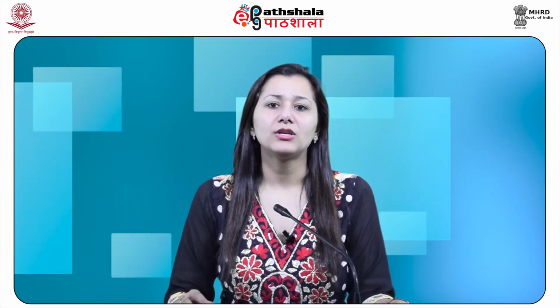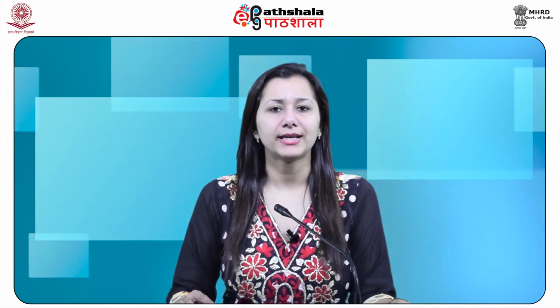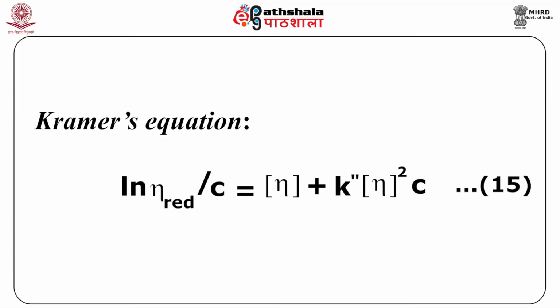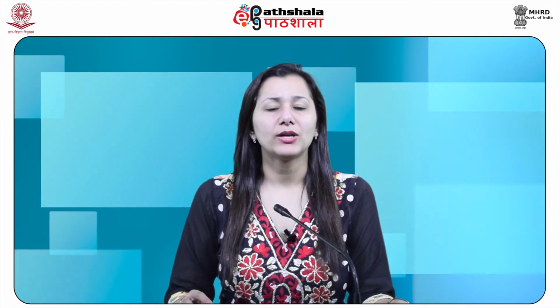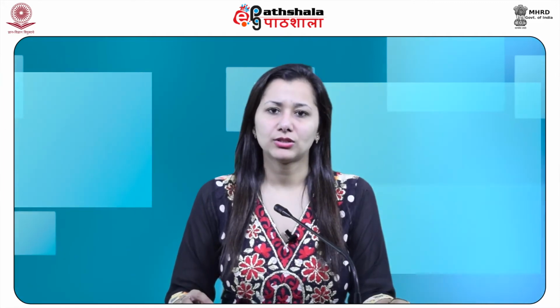The alternative definition of the intrinsic viscosity leads to the equation given by Kraemer in 1938, as shown in equation 15, as ln of eta relative by c equals intrinsic viscosity plus k double prime times intrinsic viscosity squared times c. Both these equations are applicable only in dilute solutions.